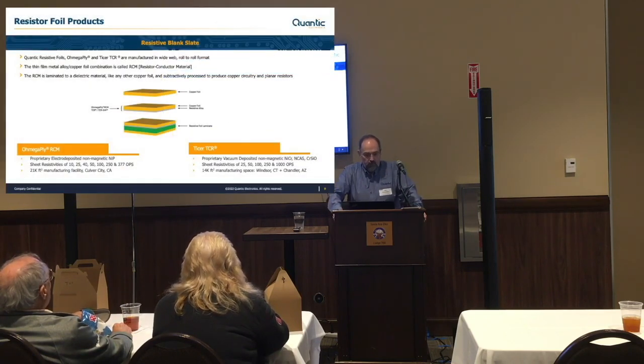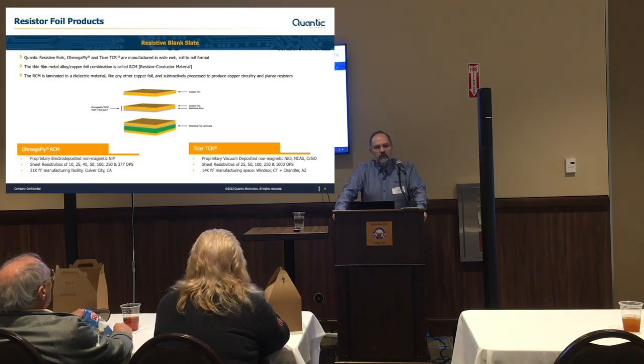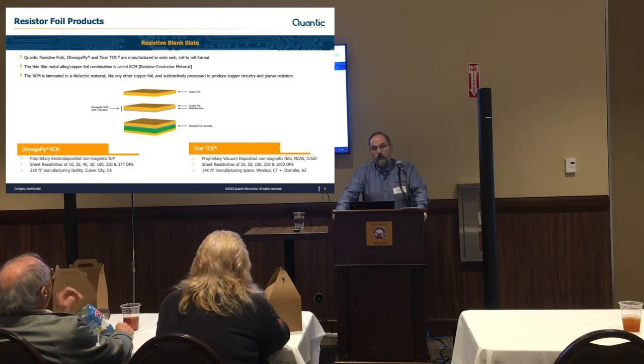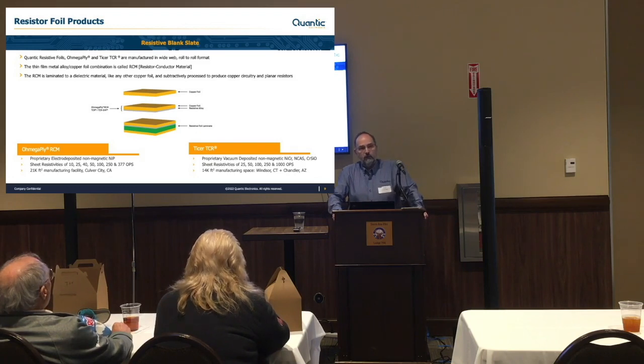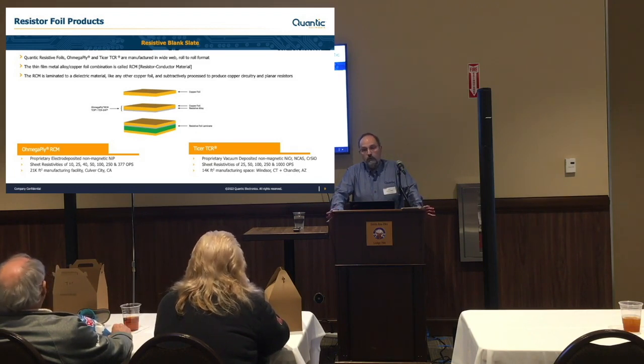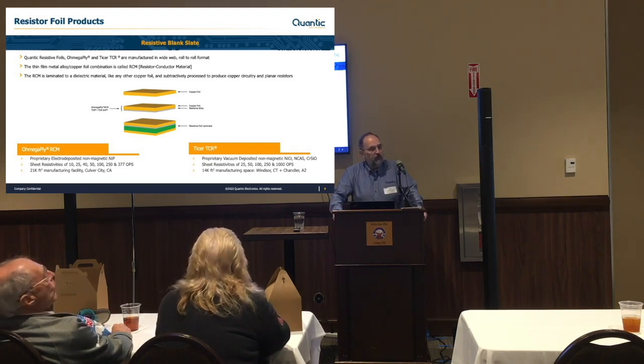So when you think about it, we're starting out with a basic resistive blank slate. We're taking copper foil, and then we're putting a resistive layer across the entire copper foil. In the case of Ohmega, like I said, we have a plating line, so we plate nickel phosphorus onto the copper foil. In the case of the Ticer material, we have a huge sputtering chamber. So it's a reel-to-reel process.